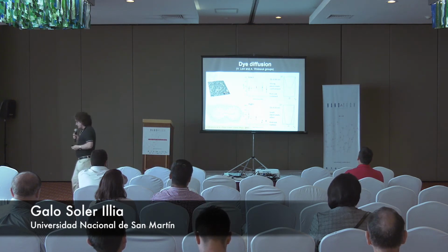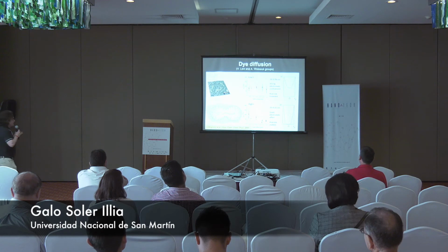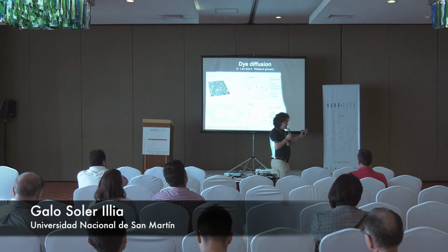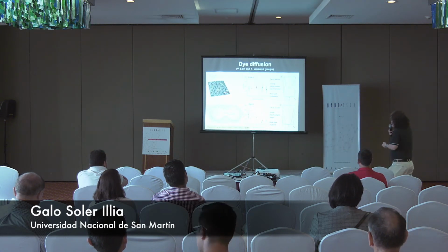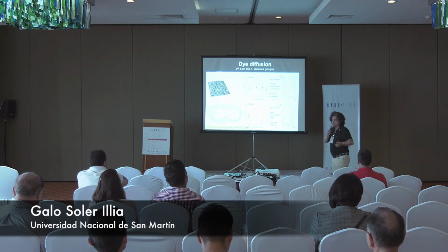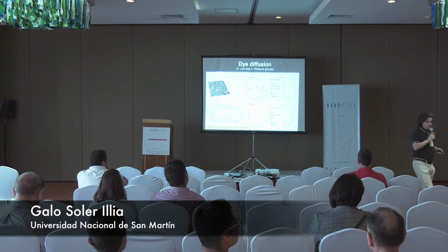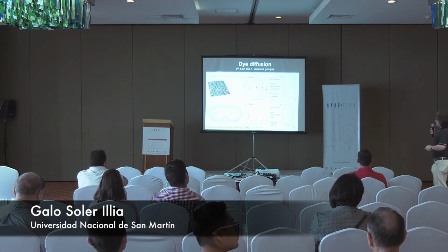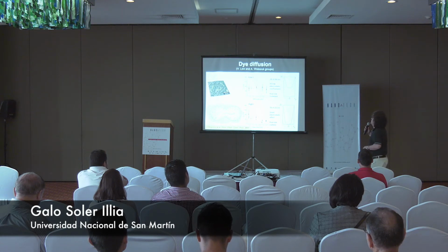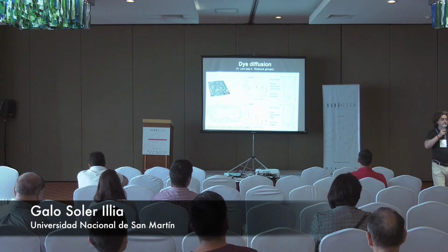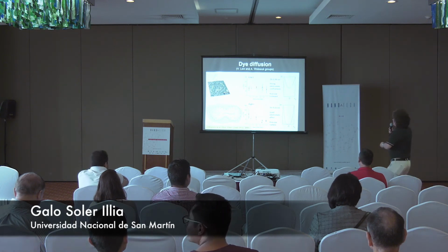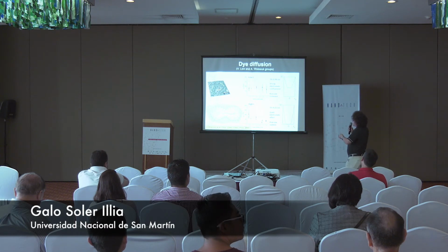Another way to look into this problem is to use more modern techniques, for example, fluorescent techniques that take a fluorescent probe and analyze its movement: fluorescence correlation spectroscopy, fluorescence recovery after photobleaching. All these kinds of techniques we applied, and we found interesting things. Here I will not go much into details, but you see a charged dye moving here, and what we observe is that at low ionic force, meaning low salt content, this is the residence time of a molecule.